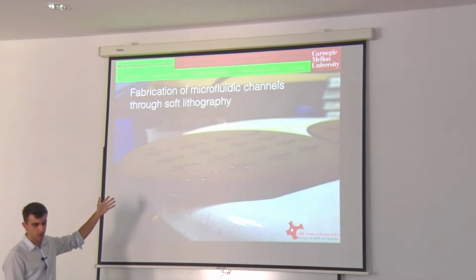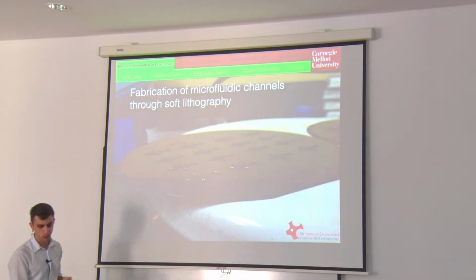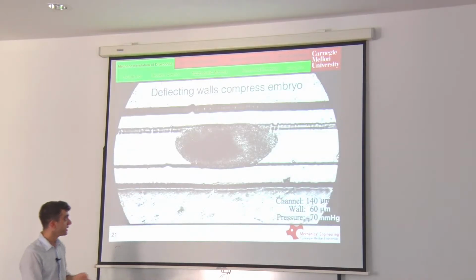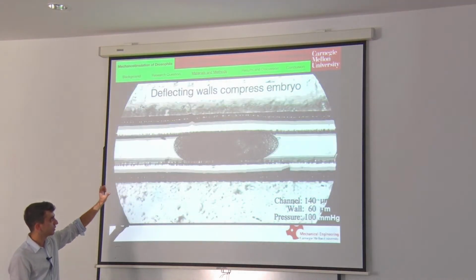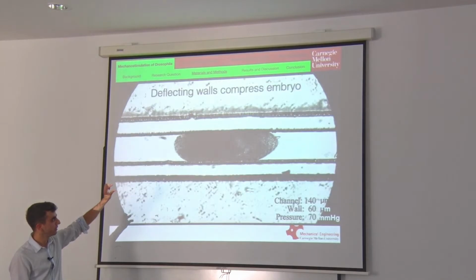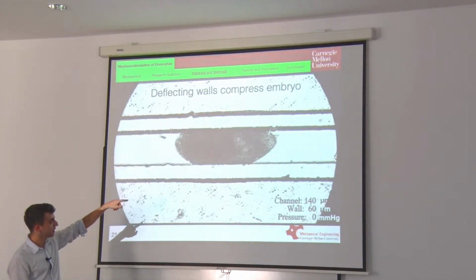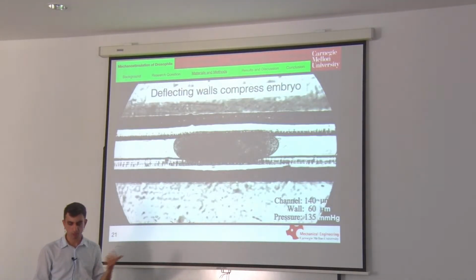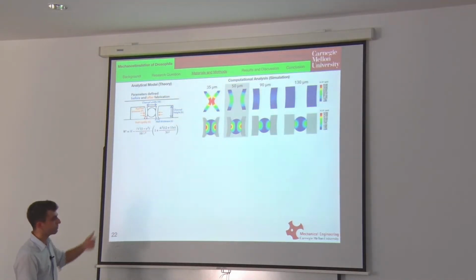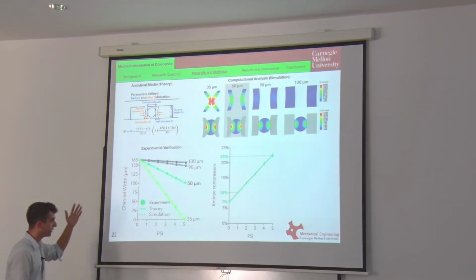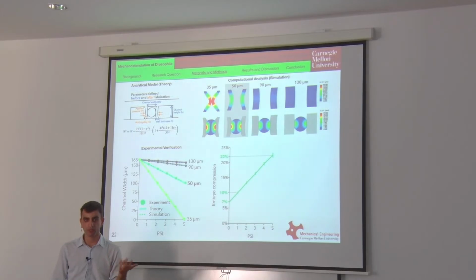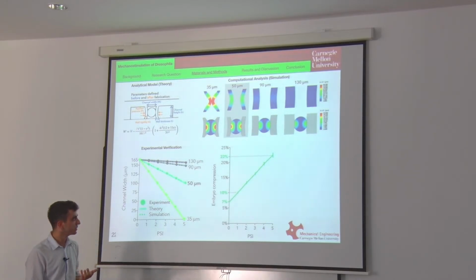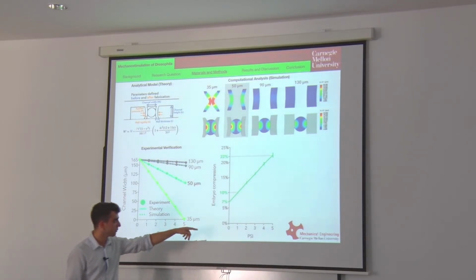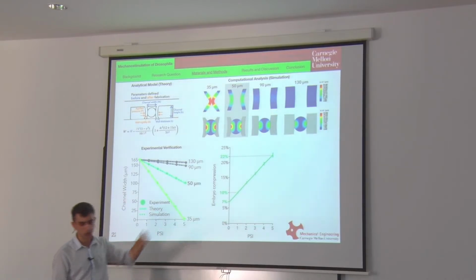And I fabricated these proof of concept models on silicon wafers, and I made PDMS devices out of them, and I put embryos in it. These embryos are really small. They are around the thickness of a hair. And by changing the pressure, as you can see, I can compress them, which works really well. And I got the experimental data as well. And it looks like the theory, experiment, and the simulation all fit each other. So I finished the characterization with this graph where I show the PSI versus embryo compression.